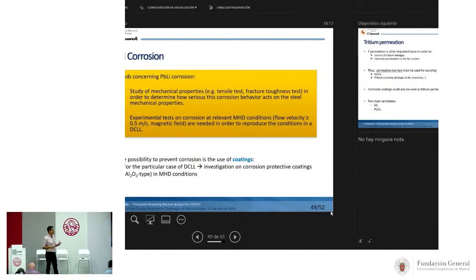So, needs concerning the corrosion due to liquid metal. We need to study the mechanical properties in order to determine how serious this corrosion behavior acts on the steel. And of course, we need experimental tests on corrosion at relevant conditions. That means at high velocity and high magnetic fields. And of course, in CMAT, we are working on that.